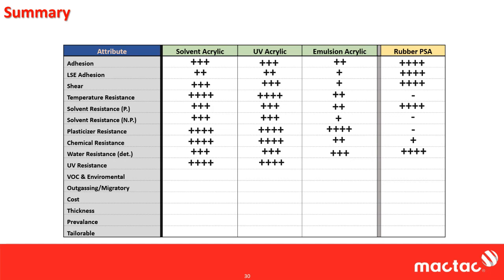UV resistance, you're going to get high UV resistance between the solvent and the UV acrylic. Emulsion, you get a little bit diminished UV resistance, and really this is more because of all the various additives that are in there. They are what's actually degrading and making it look bad. It's not the acrylic backbone itself. And rubber PSAs have very bad UV resistance.